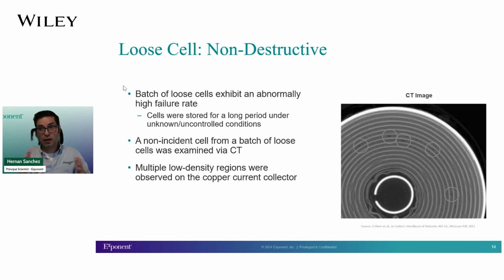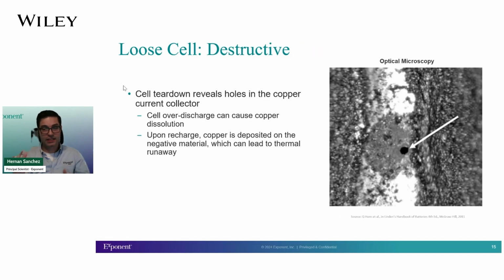And when we looked at a non-incident cell, we all of a sudden found these low density features right at the copper current collector. So once again, that guided our investigation into cell teardown. And in this case, you could see with an optical microscopy that there were holes. And like I said, the previous talk was perfect because that showed the type of copper dendrites that can be formed. And what we were seeing is the holes were due to cell over discharge.